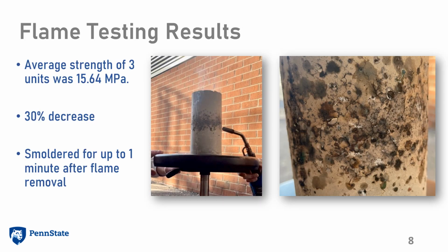In addition to the initial and secondary testing, flame testing was completed to assess how damage done by fire could affect the compression strength of the concrete. Each cylinder was rotated while a flame was held to the surface for 5 minutes. Cylinders with a 28% loading level of plastic were used, and it was determined that the average strength from the initial 28% cylinders dropped to 15.64 megapascals. This equates to a 30% decrease in compressive strength. It was also noted that the cylinders continued to smolder for up to 1 minute after the flame was removed.